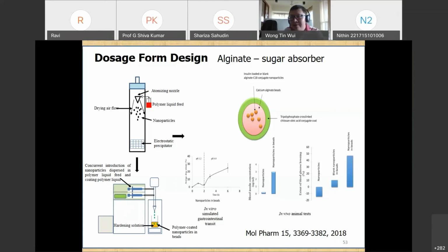And the entire nanoparticle in beads is coated with chitosan oleic acid conjugate in order to protect them from early release in the gastric phase. Now you can see that oral consumption in vivo of these structures enables good glucose lowering due to enhanced bioavailability of the insulin in the systemic circulation, right?